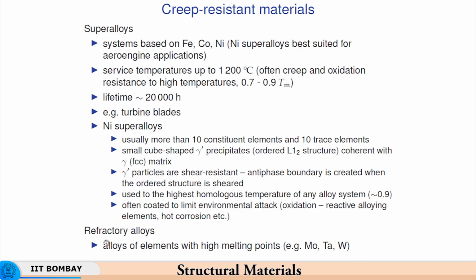So, refractory alloys are the ones which can be used, but again, although they have very high melting points, molybdenum, tantalum and tungsten, these alloys have oxidation resistance which is quite poor. For example, molybdenum forms different kinds of oxide, of which the third oxidation state, that is MoO3, is volatile and therefore it just evaporates. Even tungsten gets oxidized, and the oxide of tungsten, that is WO3, will also evaporate. So, these refractory alloys when oxidized have this weakness.